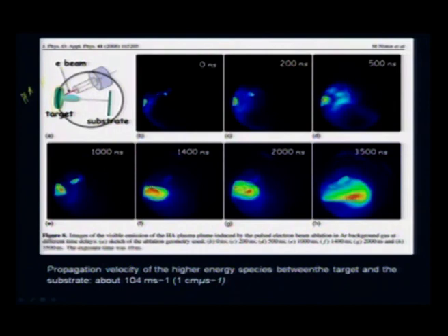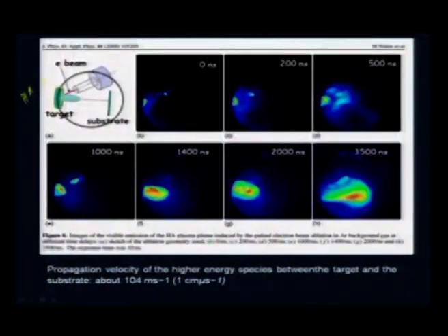Look at the progression of the plume, and this is actually a luminescing plume, because all the ions in your hydroxyapatite, usually calcium, phosphorus, all these are actually fluorescing, and once you trigger the pulse at 0 nanosecond, this is how it is, but they spatially grow with time, and that is what you see here.